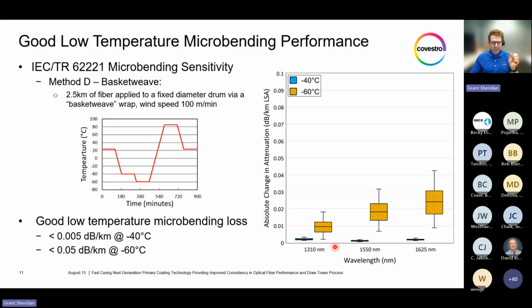So as we can see, this next generation coating provides very good low temperature microbending performance at negative 40 degrees C. We're about an order of magnitude below a threshold of 0.05 change in attenuation. So at negative 40, we were at 0.005 dB per kilometer. Now, when we do go to negative 60, we do see an order of magnitude increase relative to the negative 40 degrees data.